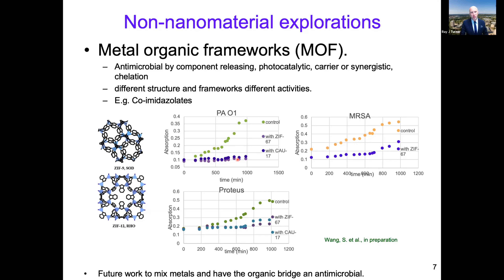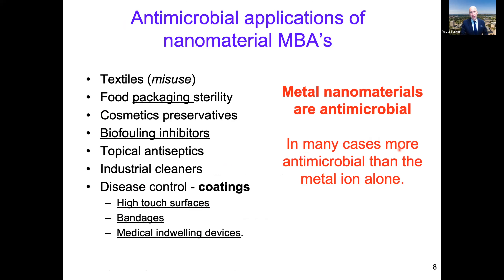Metal-organic frameworks work similarly. We've been working with cobalt imidazolates recently. Here's a growth curve without challenge and then challenge with different forms or frameworks of the MOF giving different levels of inhibition. This is methicillin-resistant Staphylococcus aureus, and we have fairly good activity — cobalt itself is not that antimicrobial, but in this MOF it is quite antimicrobial.